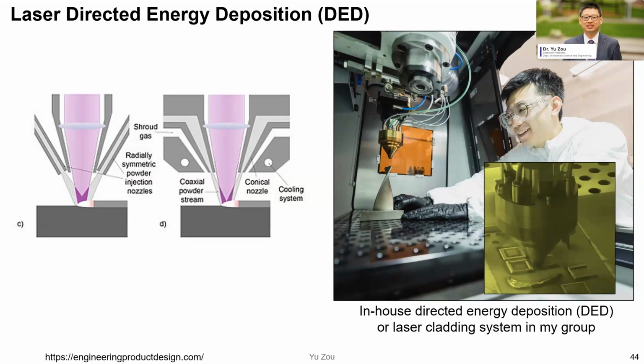Initially, laser DED is a coating technique. We also call it laser cladding. So you can see we can use the laser to clad new materials and improve the surface performance. And then layer by layer, we can make a rather bigger part with a 3D structure. People may ask, what's the main difference between laser powder fusion and DED? The main difference is DED can build up parts relatively faster and build up a larger volume, but the spatial resolution is not as good as laser powder fusion.